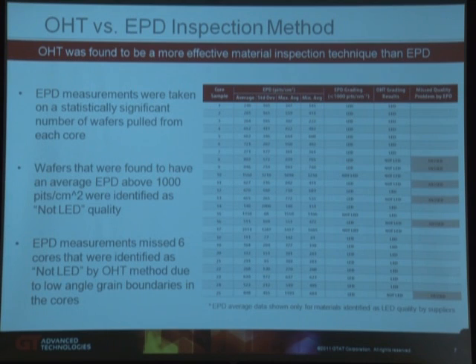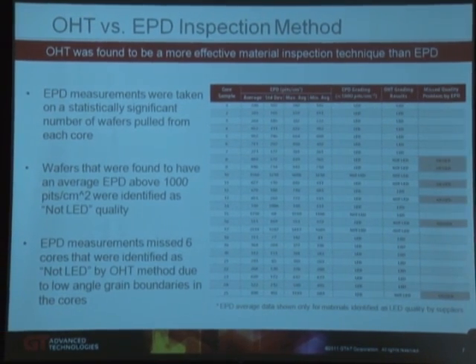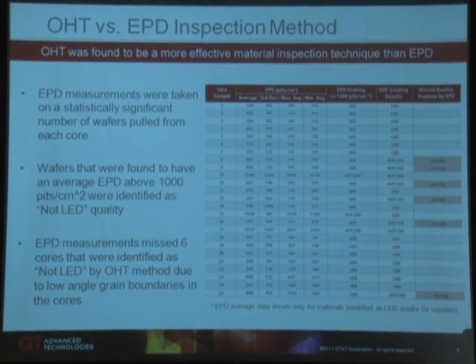Etch pit density, or EPD, measurements were taken on a statistically significant number of wafers pulled from each core. EPD has traditionally been used as the method to separate or identify LED and non-LED grade material, and it is done at the end of the wafering process on a very small sample of the core, and therefore it is a destructive test, and it is done after the wafer house has spent all of their capacity, quality, processing to process the material. Wafers that were found to have an average EPD above 1,000 pits per square centimeter were identified by us as non-LED. That's a pretty standard industry practice.